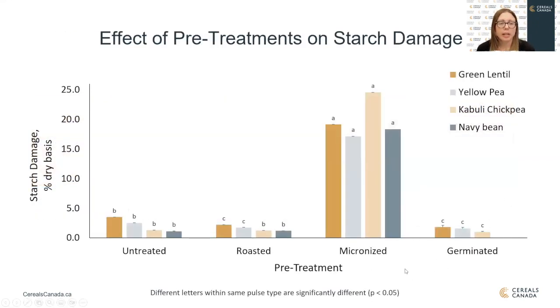So looking at starch damage, micronization had a large impact on starch damage. For the next couple of slides, these are all looking at the straight grade flours from the roller mill. You can see that for each pulse type, the micronization treatment really increased the amount of starch damage. We saw a slight decrease in starch damage for the yellow pea and green lentil roasted flours, and we also saw a decrease in the germinated flours.